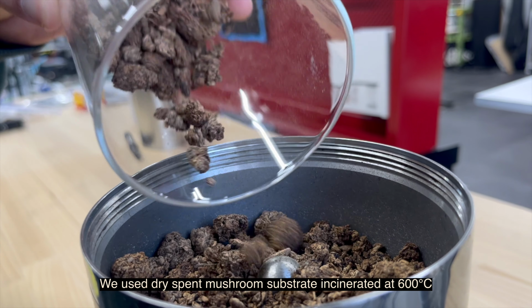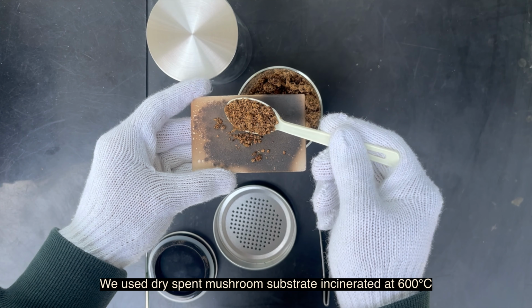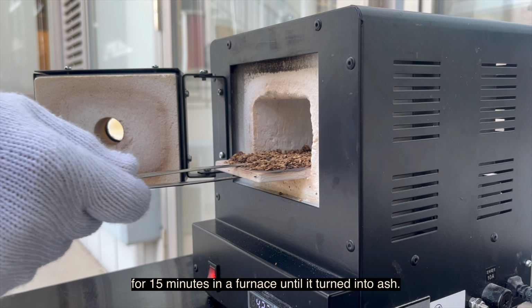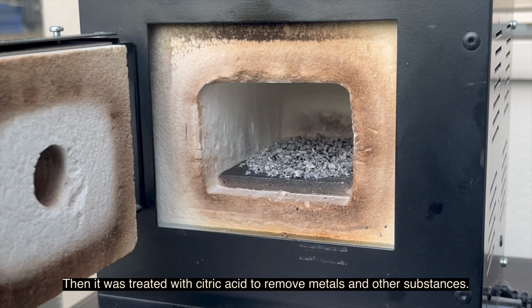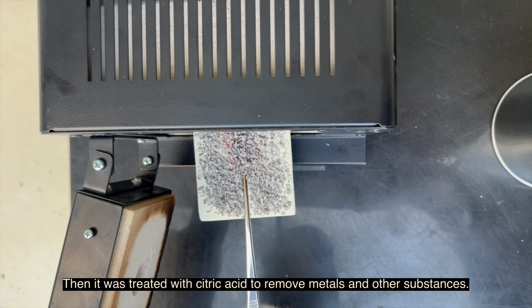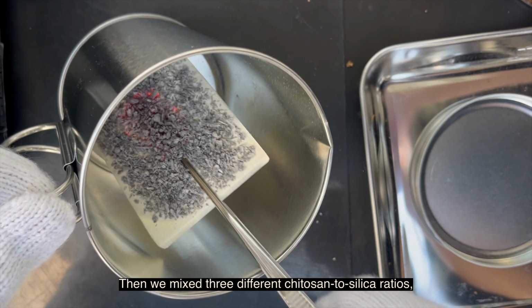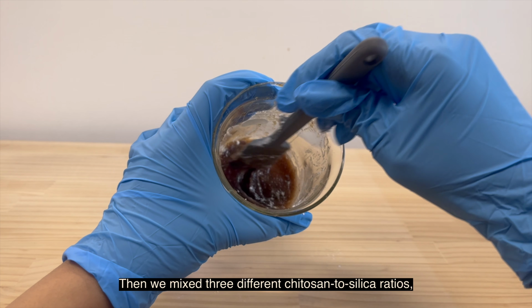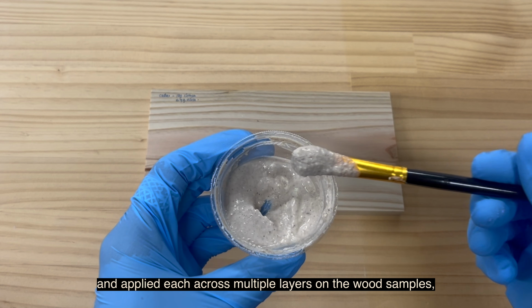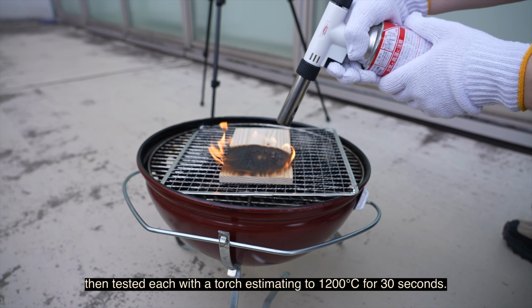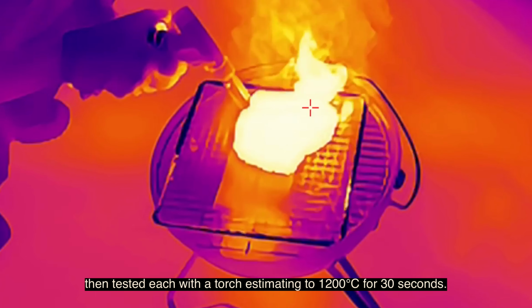We used dry spent mushroom substrate incinerated at 600 degrees Celsius for 15 minutes in a furnace until it turned into ash. Then it was treated with citric acid to remove metals and other substances. Then we mixed 3 different chitosan to silica ratios and applied each across multiple layers on the wood samples. Then we tested each with a torch estimated at 1200 degrees Celsius for 30 seconds.